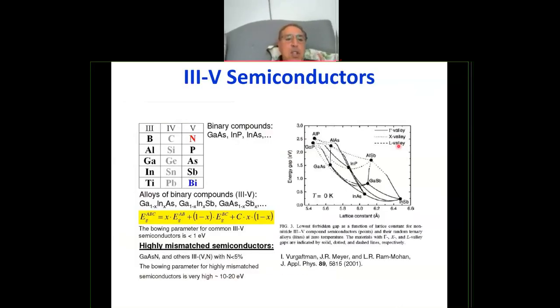So next slide. So here you can see, for example, the gallium and arsenic, and you see here nitrogen, and you see the bismuth. These are two important group 5 elements. So what we're trying to do now is replace arsenic either with nitrogen or with bismuth. Okay, and this is what the expected energy band gap should be.